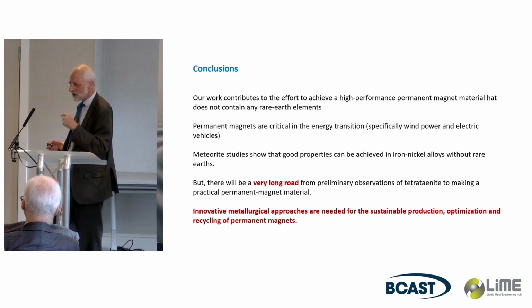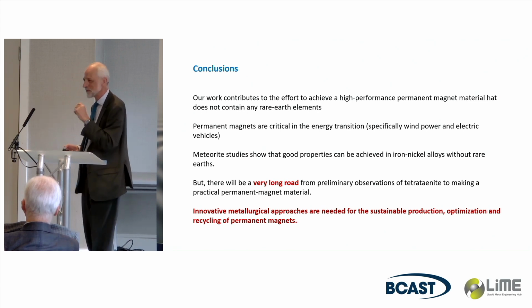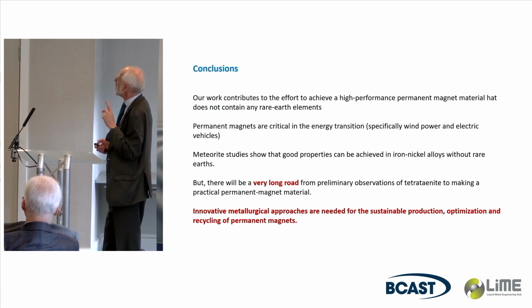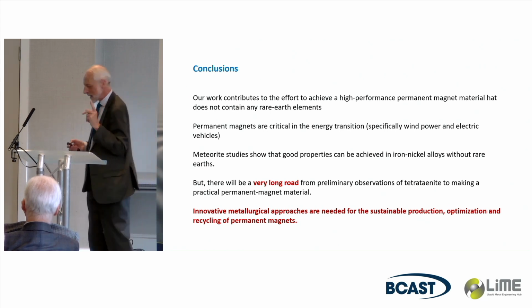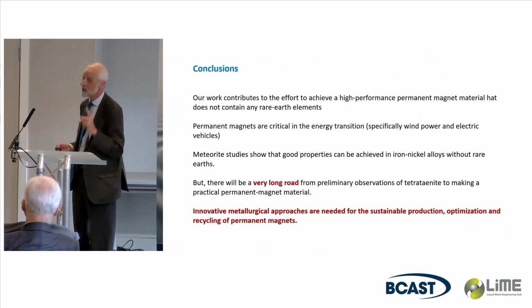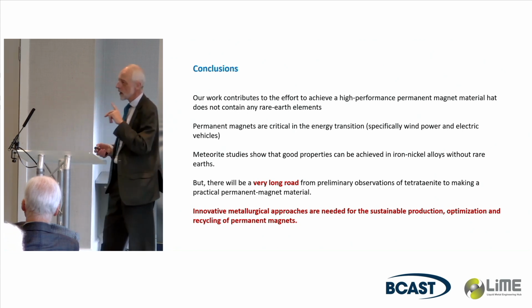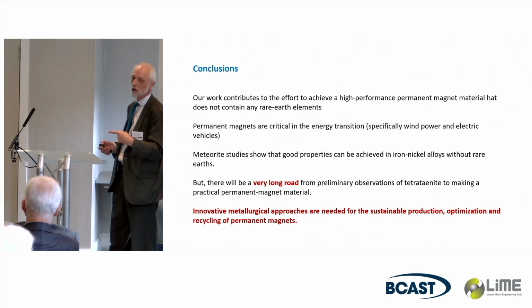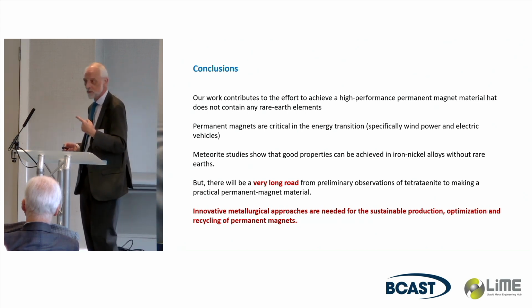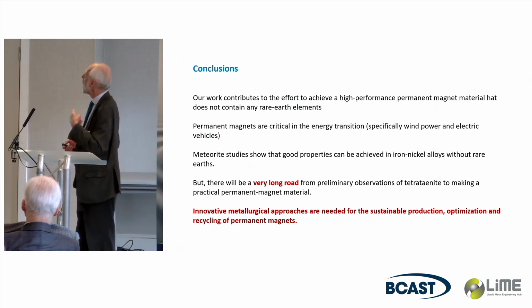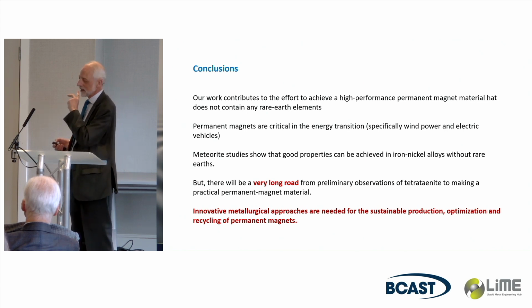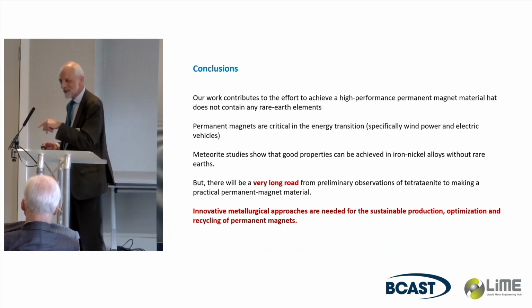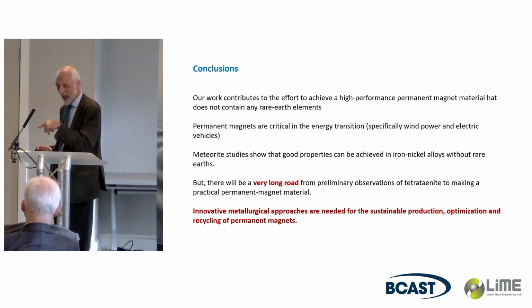So this brings us to conclusions, and I'm leaving us with time for some discussion. So I think despite the fact that we might not really have made tetrataenite, or at least not in the quantities we thought, we have highlighted the issue of composition control, in particular putting phosphorus in to speed up the diffusion. And it is clearly still an area of opportunity, because we know with absolute certainty from the meteorites that this material can exist and has good magnetic properties.